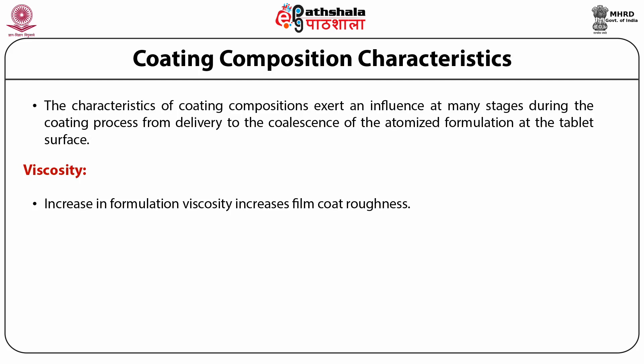Increase in formulation viscosity increases film coat roughness. Viscous solutions result in discrete droplets with a more rounded appearance, indicating a lack of spreading and droplet coalescence on the surface. Relatively less kinetic energy is required to force droplets of low viscosity to spread and coalesce on the tablet surface. As coating solution viscosity increases, there is greater resistance to spreading and reduced tendency to coalescence, both of which increase surface roughness. Dilute polymer solutions are used to impart gloss to coated tablets. The rheological properties of coating compositions depend mainly on polymer size, shape, polymer-polymer and polymer-solvent interactions, polymer concentration, coating composition temperature, and viscosity of solvent. Lower viscosity-grade polymers permit higher solid content and lower solvent content, resulting in shorter processing time.